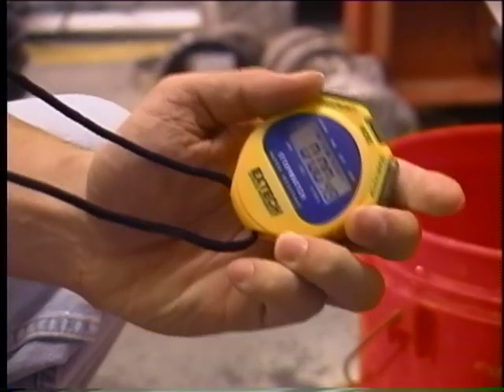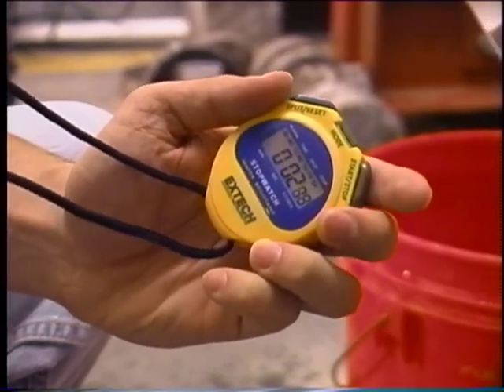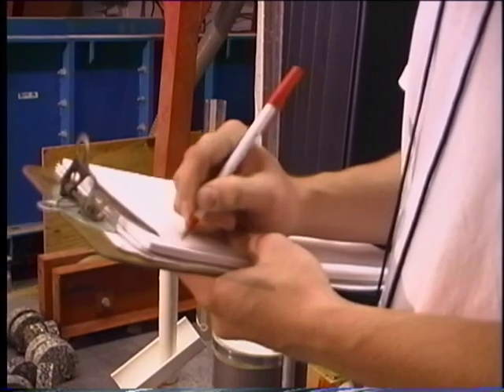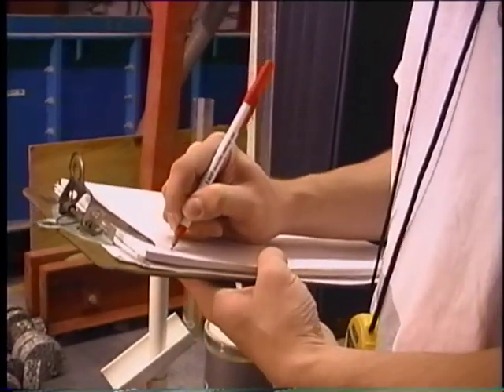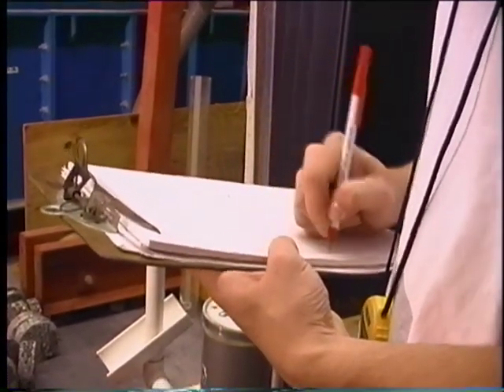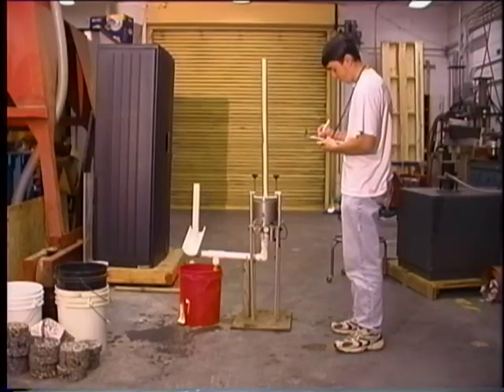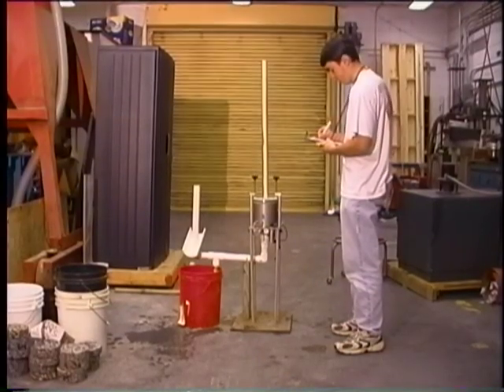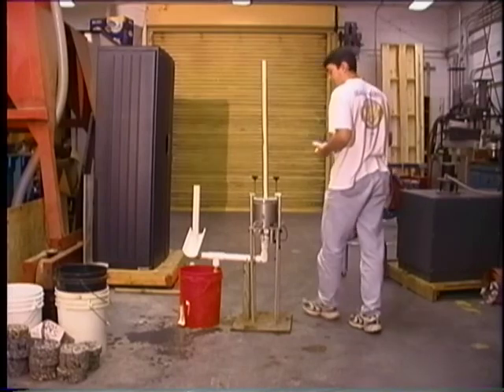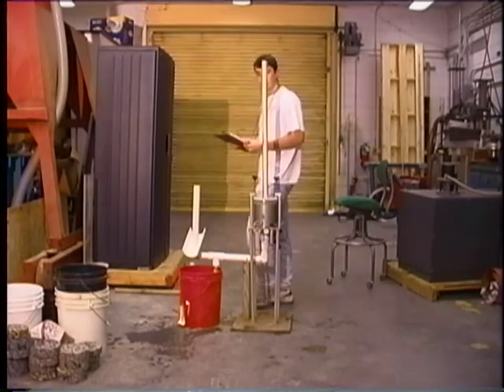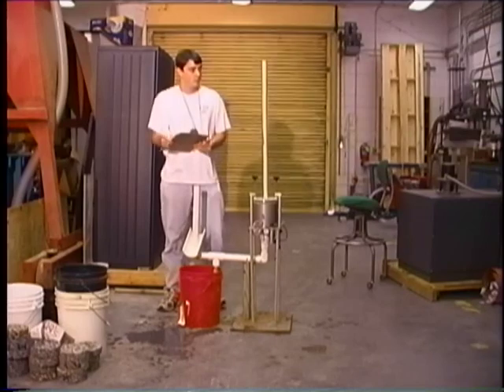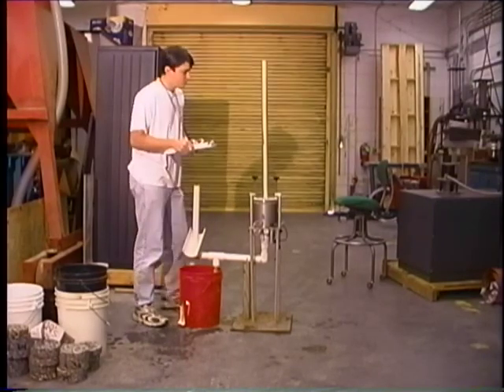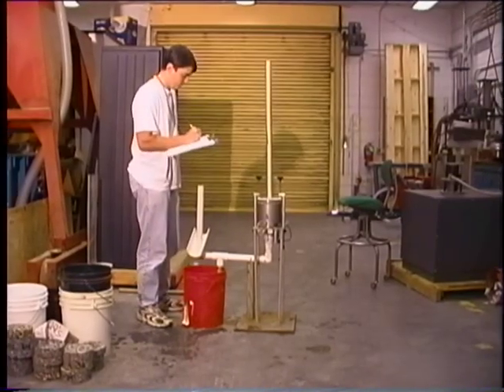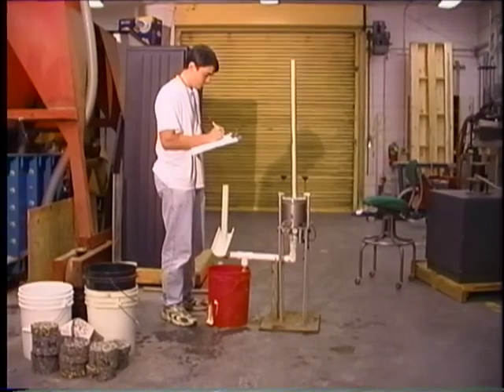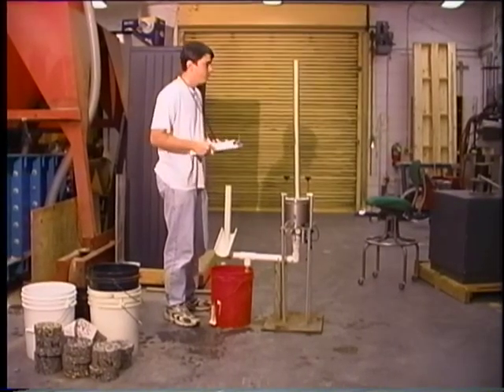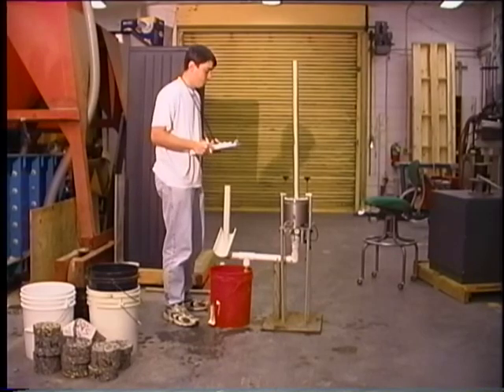The timer is used to record the times as the water falls through the sample. If the water is falling fast, record the heights every 5 seconds. If the sample is taking a few minutes to finish, record heights at 30-second or 1-minute intervals. If water is falling slowly, record the heights every minute until 5 minutes, then at 10 and 15 minutes. After the 15-minute mark, record times every 15 minutes until 2 hours have passed.